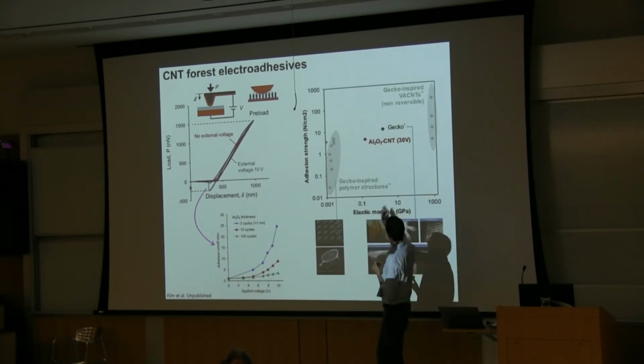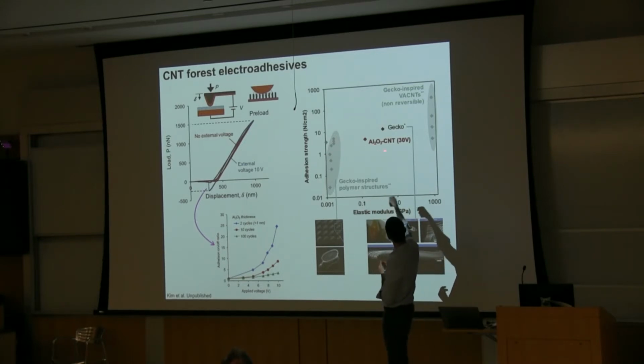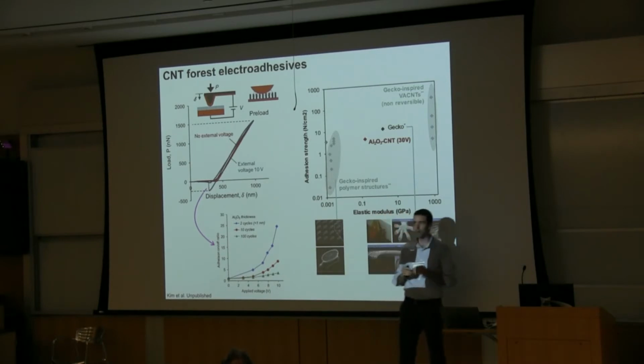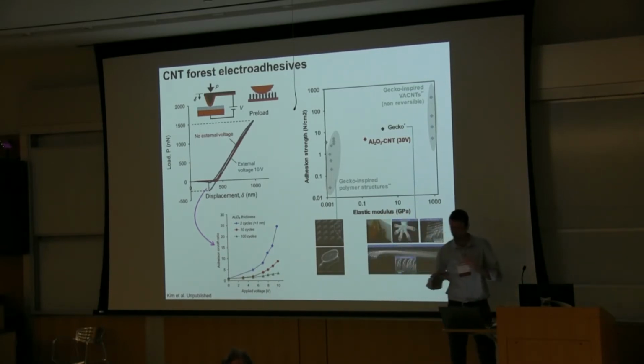And so far we've been able to get roughly 10 newtons per square centimeter between 1 and 10, which is in the same realm of a gecko adhesive, but we haven't built a robot that can climb a wall. This is just the extrapolation for this adhesion. So this kind of surface engineering at fine scales is probably pretty interesting for manufacturing as well.